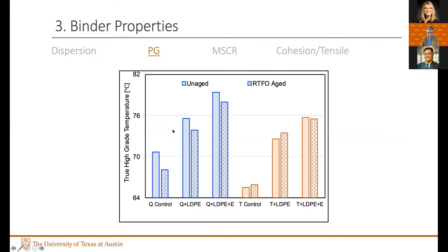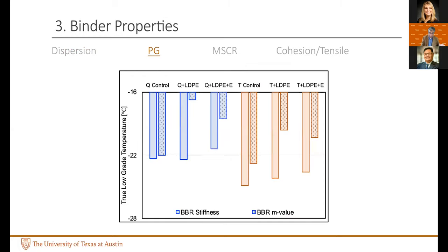Some of the standard tests like the PG, you would see that whether you take the unaged or RTFO aged, the high temperature grade, you see the same stiffness increase that we saw in asphalt mixtures, whether it was the Qatar binder or the Texas binder. This is very consistent, the increase in stiffness. Corresponding to that, if you look at the low temperature properties, this is a low temperature grade stiffness measurement using the BBR. And if you look at the S value, it reduces, but not a whole lot. It's not very significant for both binders.